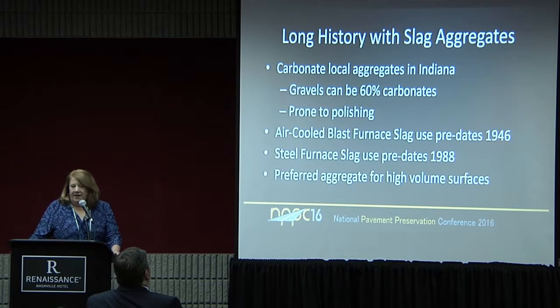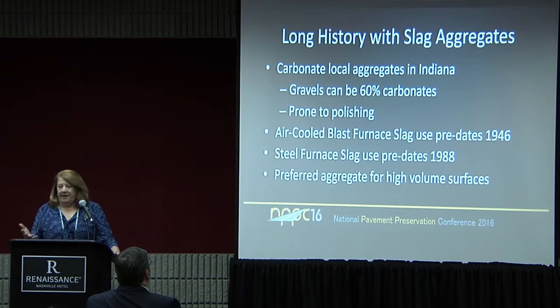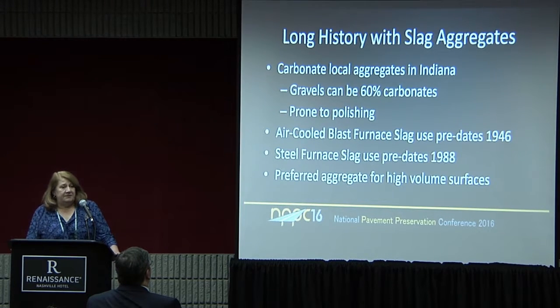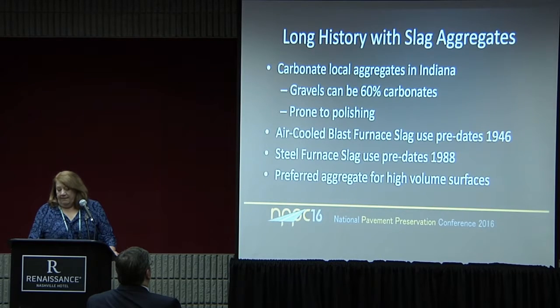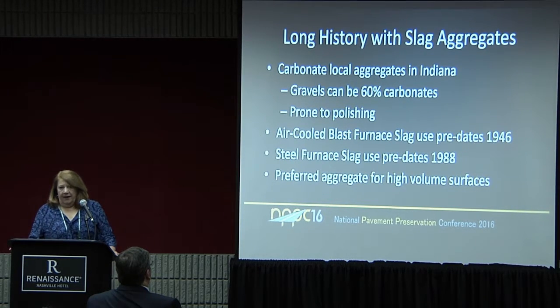So I mentioned the kind of crummy aggregates that we have from a frictional point of view in the Midwest. Our gravels may be 60% carbonates. So even if we try to use a gravel, it may be prone to polishing. So the standard in Indiana and several other states in the area is to blend these materials with a harder, higher quality, higher friction quality aggregate.